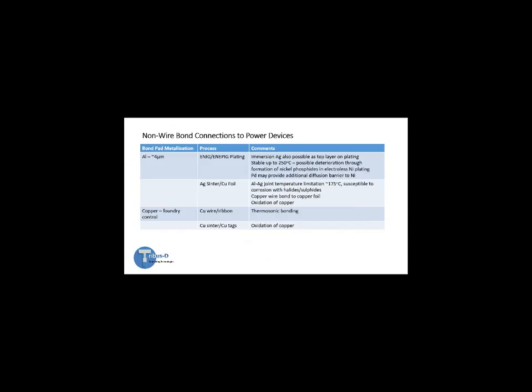So plating of the aluminium using electroless nickel, and electroless nickel, electroless palladium, and immersion gold are ways of converting the aluminium top surface to something which could be suitable for sintering and soldering. But going to high temperatures, you also need to be aware that within the electroless nickel plating, there's a level of phosphorus, and above 250 degrees C, nickel phosphides begin to form, which by their nature as intermetallics, are brittle.